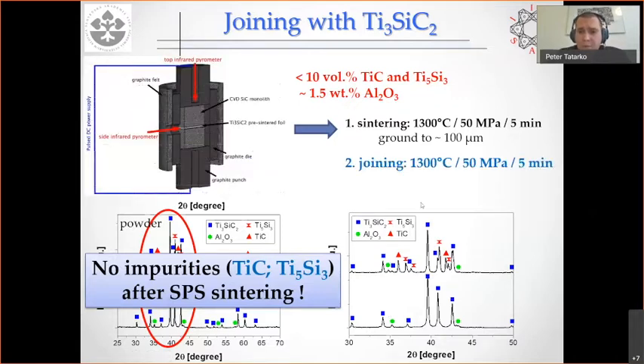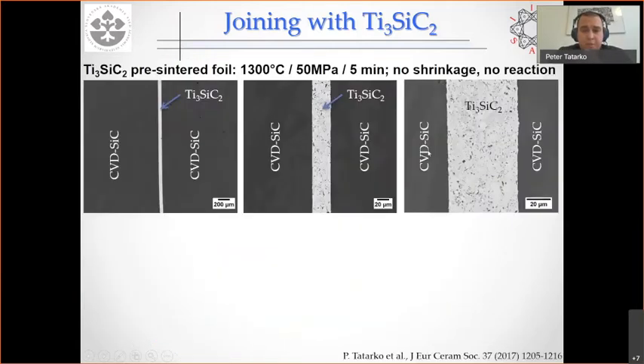Then we ground this material to around 100 micrometers, and we inserted this 100 micrometer foil between two silicon carbide pieces, and then we used SPS at the same temperature as we synthesized and sintered this material. The first very clear and very nice result was when we looked at the cross section of this joint. You can see in this case we didn't have any shrinkage. If you remember the nail-like structure, here there is nothing. So the interface was very clear, very smooth and very nice. So we were happy about that.